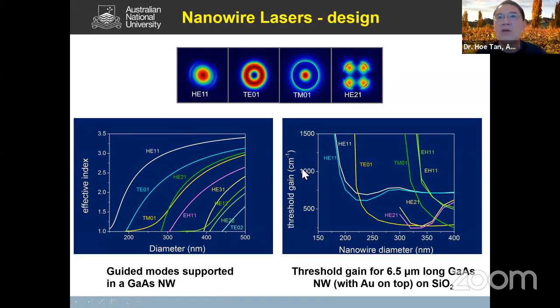Similarly, when you are making a laser, you want to have the lowest threshold gain because you want to pump the nanowire, but you don't want to pump it so hard that it burns before it starts to laser. So we want to have the lowest threshold. And if you look at the calculation that we've done here, the lowest threshold gain occurs for the larger diameter nanowire.